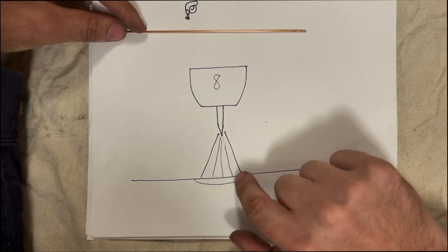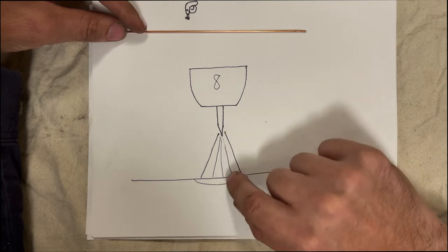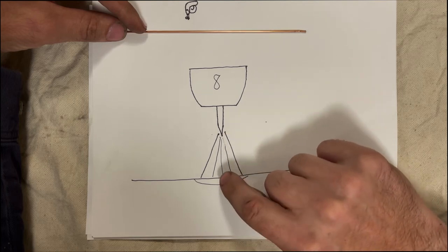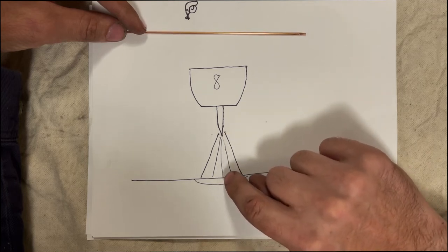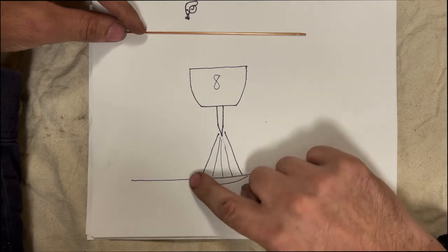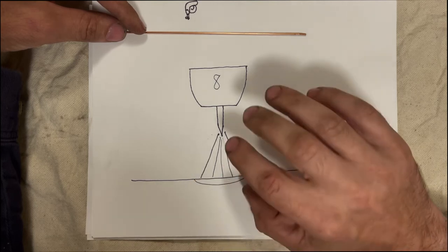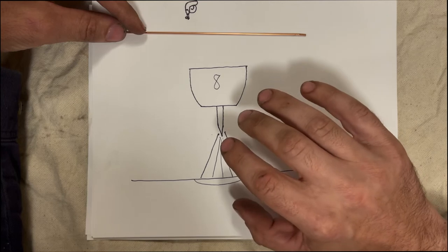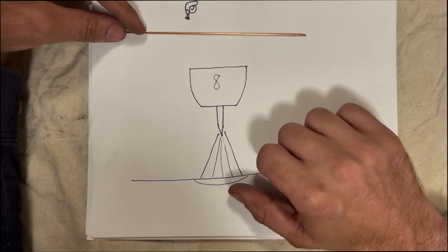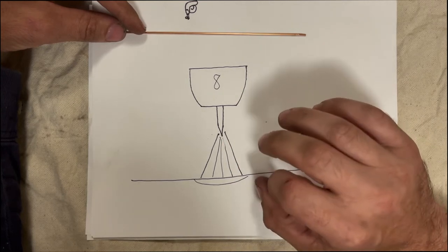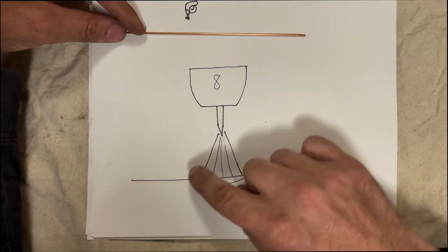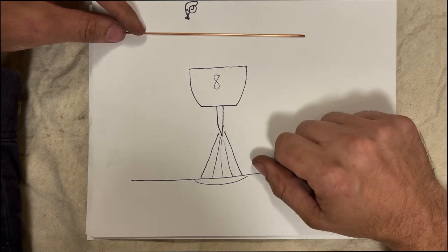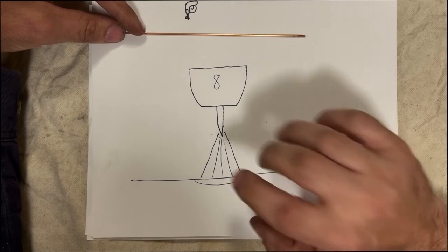The arc will start to wander around once the arc gap exceeds, I would say, about 3/16 of an inch or so, maybe a little bit more than that. The arc will start wandering. The weld puddle will start pooling weird, where rather than having a nice defined shape, it'll start looking like a kidney bean or something where it's all oblong. So you want to keep a tight arc.